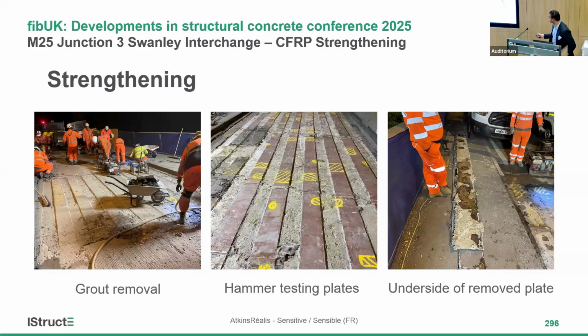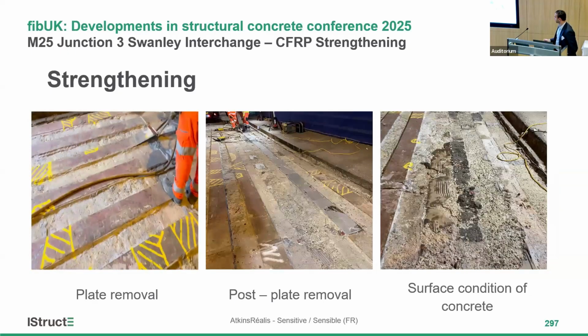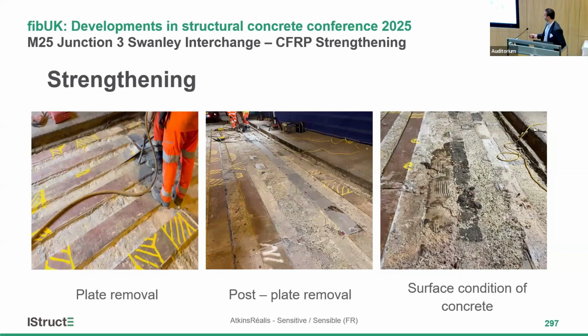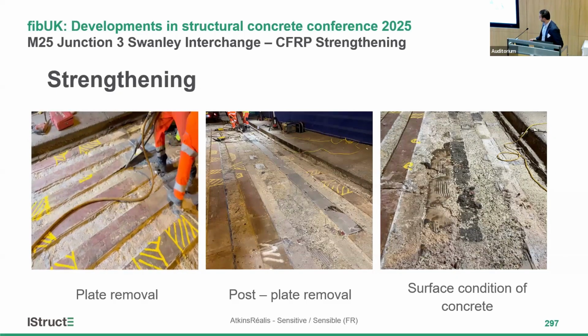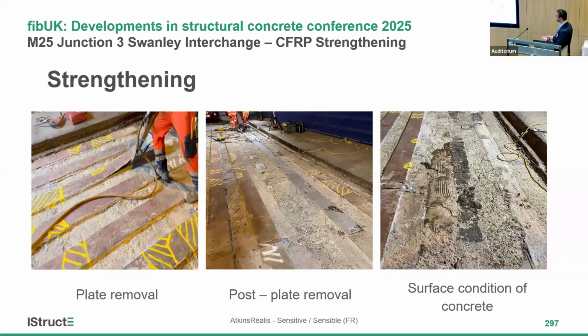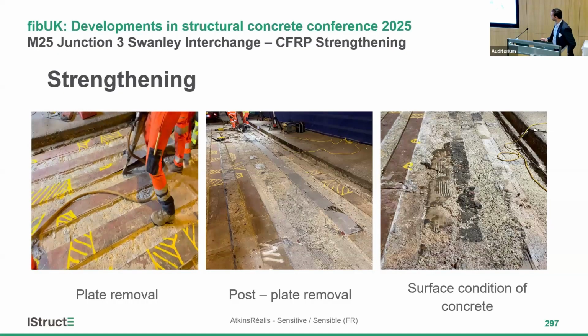So this is the first step where we have the grout removal. And this picture shows the hammer testing of the plates, where we have identified the debonding of the steel plates from the concrete surface. And this is the underside of the removed steel plate. This is the process of removal, where they're removing the steel plate one by one.